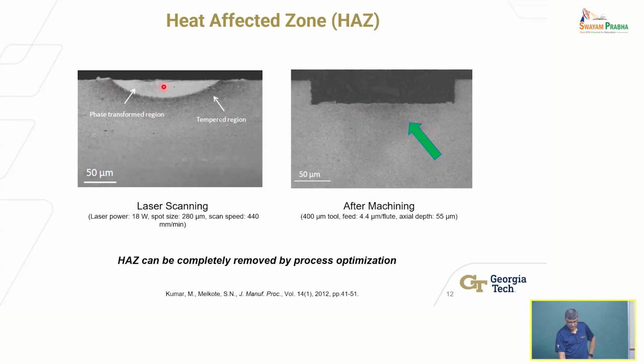So what this shows you is the effect of laser scanning. This is just showing you that, hey, if I were to scan under these conditions, 18 watts, whatever you see here, at some speed of scanning, you can see that there is a microstructural transformation. The material is a steel. It actually gets transformed, right? It produces what appears to be white, generally much harder. It typically is. But if you do it in situ, remember, the idea is to heat it and soften it and cut in situ, right? Not wait for it to come to room temperature and then cut. If you do that, it'll be worse, right? Forces will be higher because this is much harder. This white region is much harder.